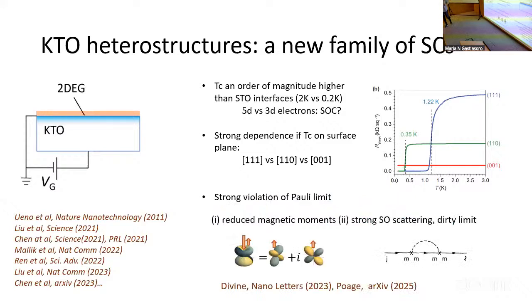Something also very interesting that happens in this system is that there is a strong violation of the Pauli limit, and what that means, and why that is typically interesting, is that superconductivity does not like magnetic fields, so it expels them. As I said, that's the Meissner effect, but it cannot expel them forever. At some point, it's like, look, energetically this is not favorable, I'm no longer happy, I'm going to go to the normal state. That's why in the beginning they couldn't make electromagnets with very high fields.